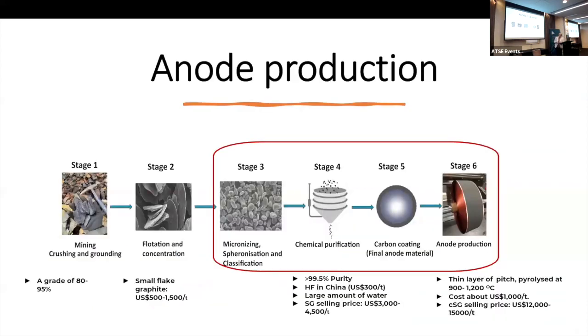So in anode production, it's using natural graphite. You mine it, you crush it, you grind it, you do a flotation and concentration process. The two important processes here are spheronization. I don't have time to go into any detail there, but you need to make spheroids of the graphite, so it's got a lot of edge planes so that the lithium can impregnate between the layers.